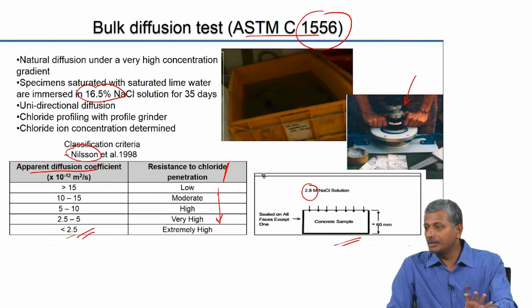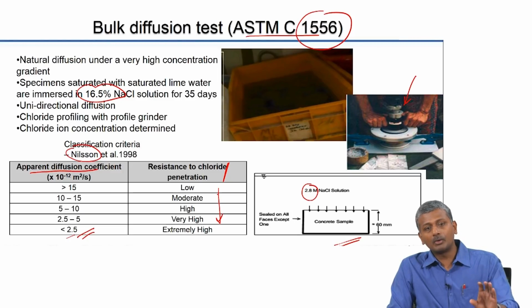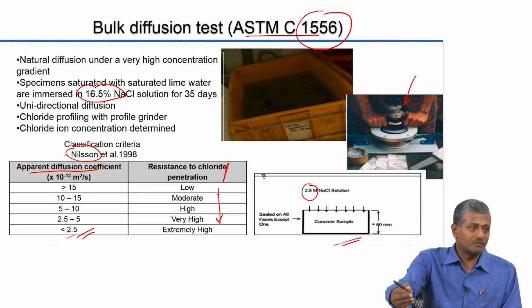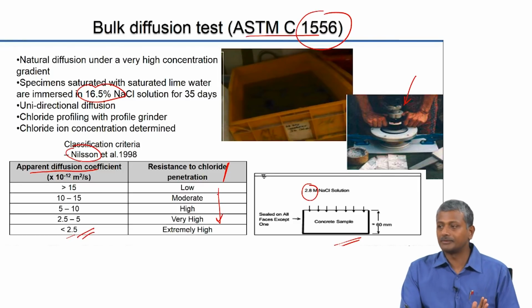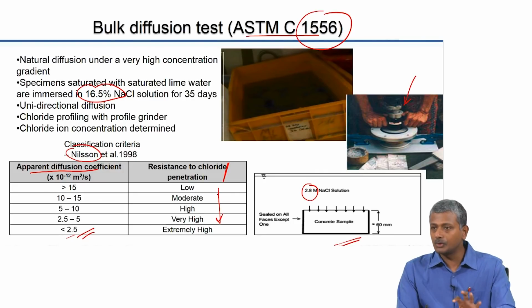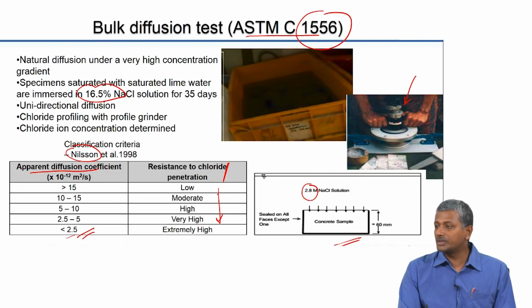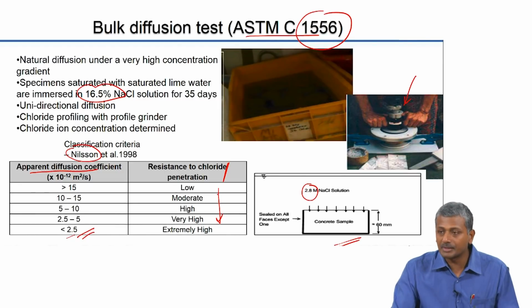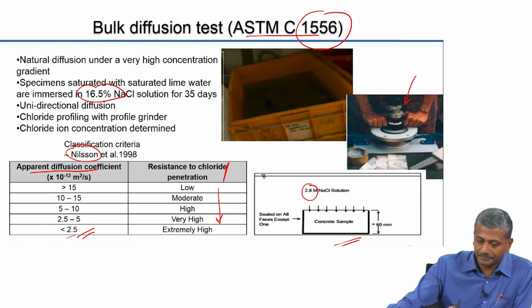Okay, please remember this is only chloride diffusion, right? We are not talking about how that leads to corrosion of the steel. We are still only talking about how much chloride can actually get into the system. So, this is the resistance to chloride penetration that the bulk diffusion test is telling you. So, we need to use the right terminology always. We need to ensure that we are addressing what is being measured correctly. Okay. So, when you come to the next few tests, when we talk about migration for instance, you will see that the chloride is driven into the concrete under a potential gradient and not a diffusion, not really a concentration gradient. Okay. So, that is something that we need to address properly by using the right terms.